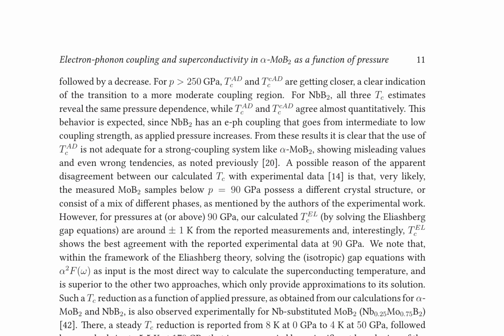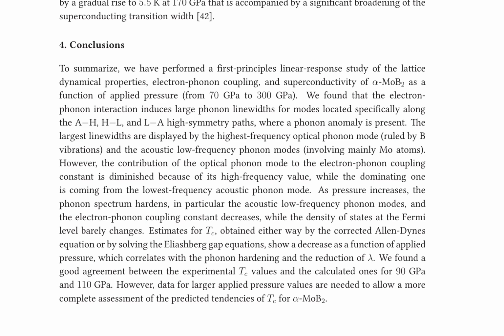As pressure increases, the phonon spectrum hardens, especially the low-frequency acoustic phonon modes, and the electron-phonon coupling constant decreases. The density of states at the Fermi level remains relatively unchanged. Estimates for Tc, calculated using the corrected Allen-Dynes equation or by solving the Eliashberg gap equations, show a decrease with applied pressure, correlating with phonon hardening and the reduction of lambda. Experimental Tc values agree well with calculated ones at 90 gigapascals and 110 gigapascals, but more data for higher pressures is needed to fully assess Tc trends for alpha MoB2.